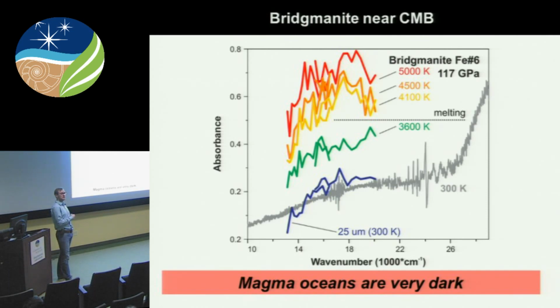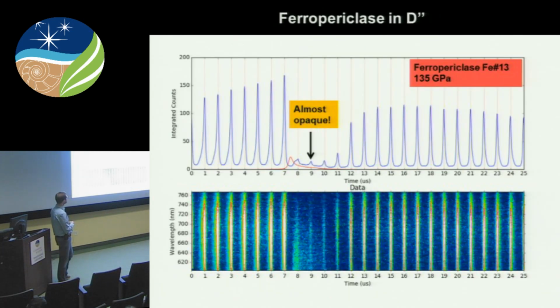But then you change the temperature by only a few hundred degrees Kelvin downward, and you get an absorption spectrum that is very different from what you have at 4,000 Kelvin. And this is the temperature range where you would expect melting or crystallization for this mineral at this pressure. So in my opinion, what we're looking at is a change in optical properties that's related to the crystallization of Bridgmanite melt. And then again, you end up with a sample at around the 25th microsecond with a spectrum that is very comparable to what you had before laser heating.